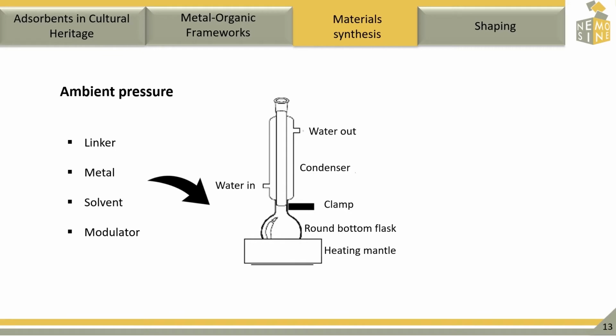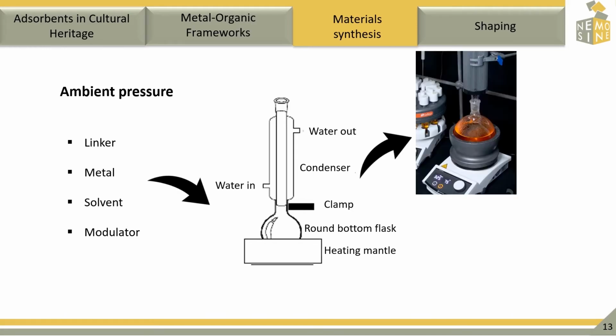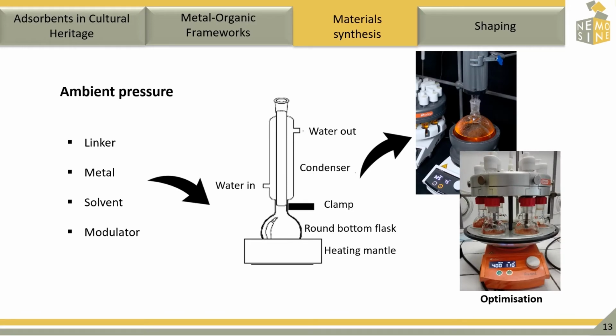Another method that we employ in our group is ambient pressure synthesis. This consists of adding the precursors, such as the linker, the metal source, and the solvent, and possibly a modulator, to a reactor that is maintained at ambient pressure and that can be heated. The mixture is stirred, and when heated, a condenser is required in order to avoid evaporation. This can be done in a single setup or in a multiple setup when we are considering optimization. Depending on the material produced, after certain hours or days, we will have a precipitate of the MOF, which can be collected either by filtration or centrifugation.